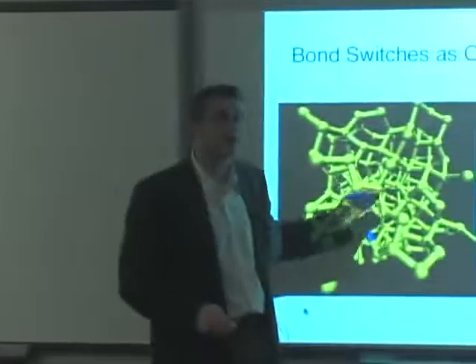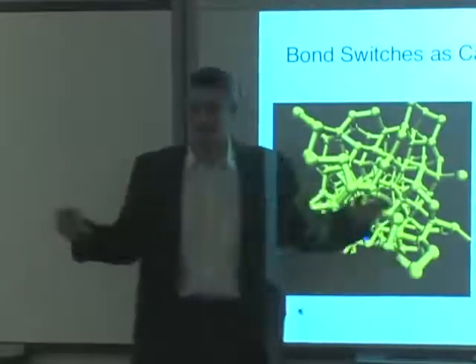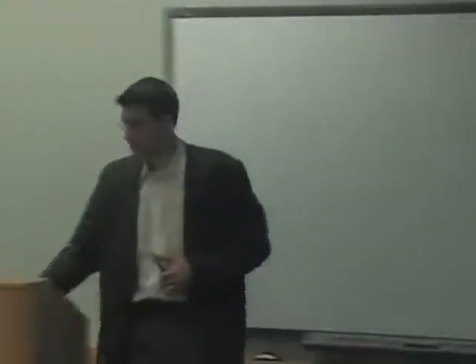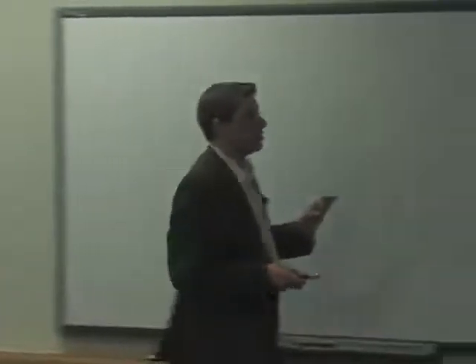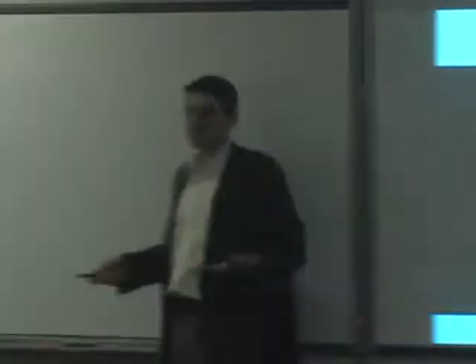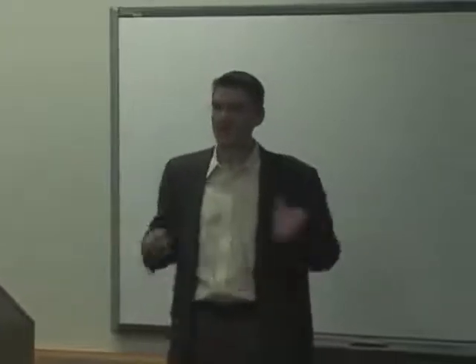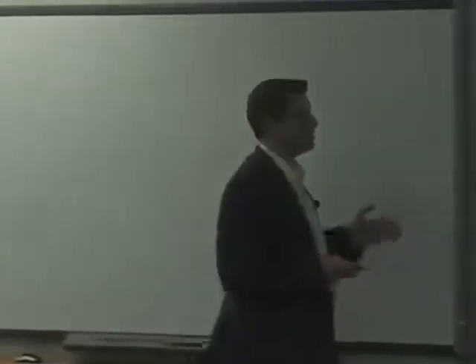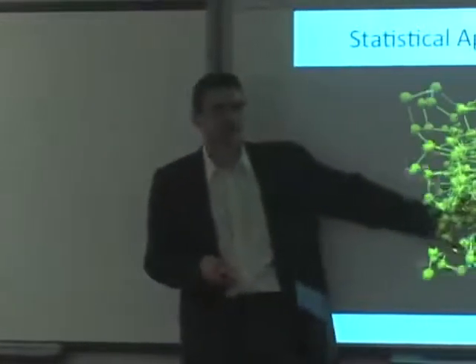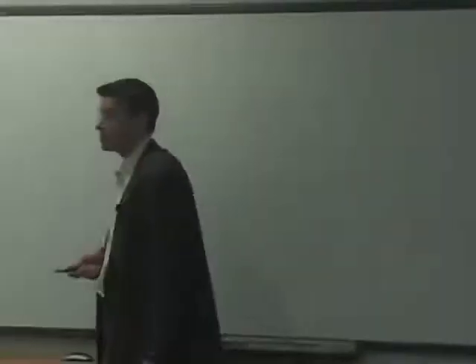Really quickly, in the computation, and this is important, you cannot study an amorphous material computationally on just one sample. You'll get anything you want, right? So you have to take a statistical approach. And really, you can't just take 10 either. That's not near enough, right? You need thousands. And so that's what we do. We generate thousands of samples using a Monte Carlo approach. We relax them all. We anneal them in density functional theory, and we relax them further. And we generate data sets that we can actually get statistics on.